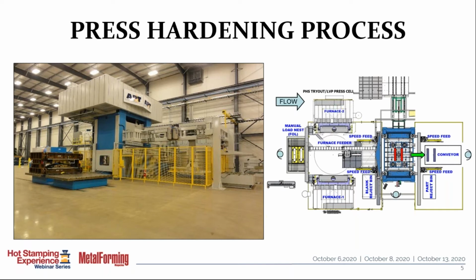So the PHS process, as was explained, is a little bit unique because it's a combination of hot forming, where the heat makes it easy to form the parts, and heat treatment, because we're going through phase transformation from austenite to martensite and creating a very tough and strong part, the strongest part in the industry, in one step.